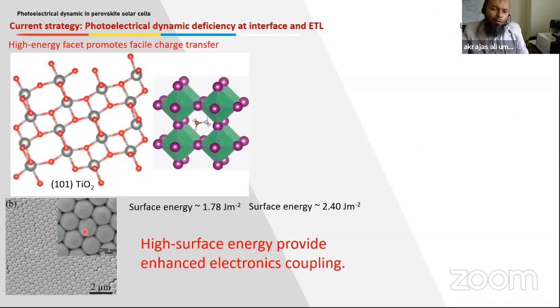For conventional spherical colloidal anatase TiO2, the surface of the particle is actually bounded by the 101 facet, which is low in surface energy, actually the most stable facet in anatase TiO2. When this material is brought into contact with perovskite, we can expect a weak coupling between TiO2 and perovskite. So what happens during the photovoltaic process is that, because of weak coupling, only a limited number of electrons can be successfully transferred to the TiO2. So most of them will accumulate on the surface of the perovskite, which will in turn drive recombination via band-to-band recombination or defect-assisted recombination.